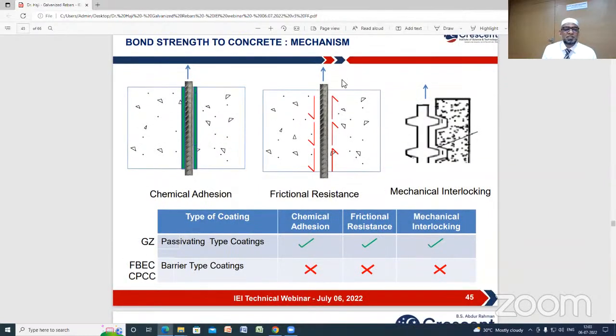We have to understand what contributes to bond strength between steel and concrete. First is chemical adhesion, the adhesion of the cement hydrates to the steel, which offers bond strength. Another is frictional resistance: when we pull the rebar from the concrete, the concrete has to move against the rebar, creating friction. That is also one component of the bond strength. Another one is mechanical interlocking. Now we are using ribbed rebar, so between the ribs the concrete will be there. When the rod is pulled, the rib portion will give some resistance. These are the three contributory factors for bond strength development between steel and concrete.